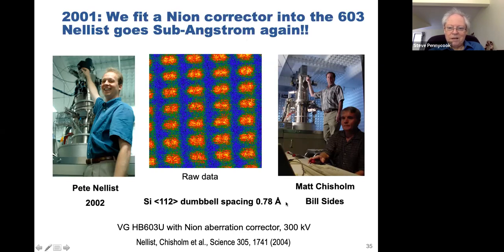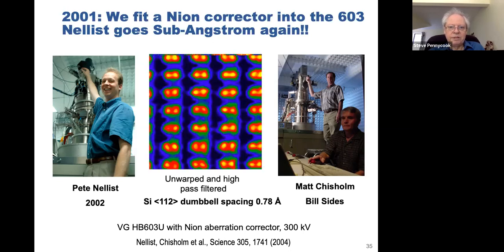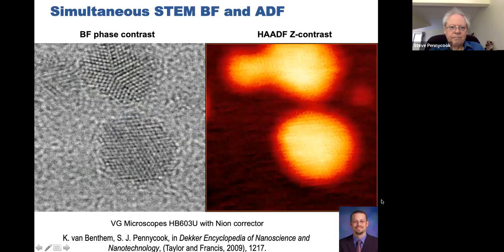Well, and with Matt Chisholm, they managed to get, this is silicon in the 112 orientation. So these dumbbells are actually just 0.78 angstrom apart. And it's a little bit noisy, but if you clean it up, you can really see all the dumbbells are nicely split. So this is very clear resolution from silicon 112.